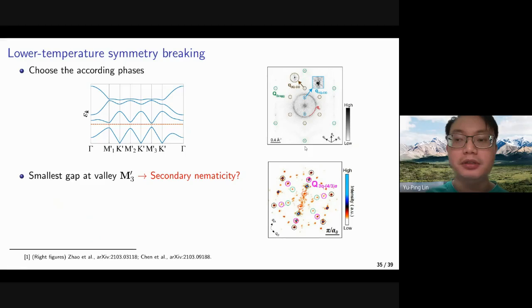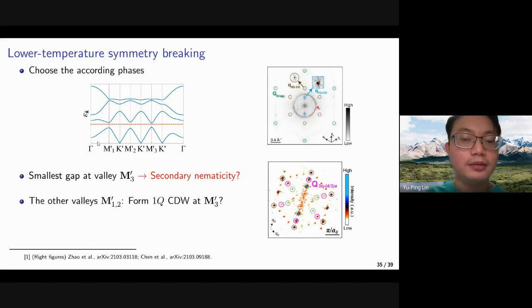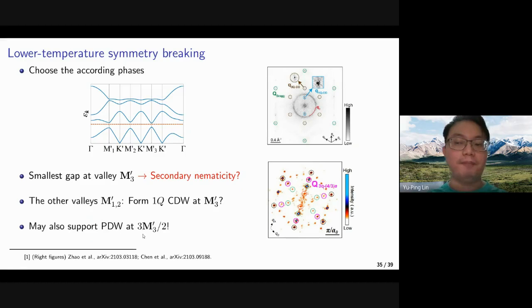So indeed, it corresponds to the rotation symmetry breaking along this direction. Meanwhile, the other valleys may be able to develop a 1Q charge density wave. And because the momenta difference between these two valleys are equivalent to M3 prime, it could correspond to the 1Q order here. So maybe this is just the 1Q order. And this kind of valley theories may also support the pair density waves at the 3-half cell point momenta.